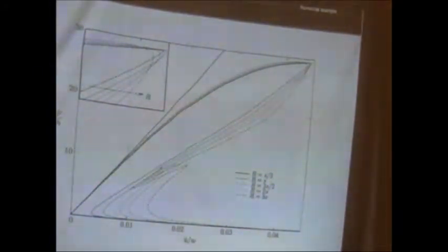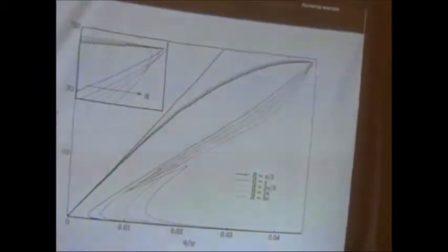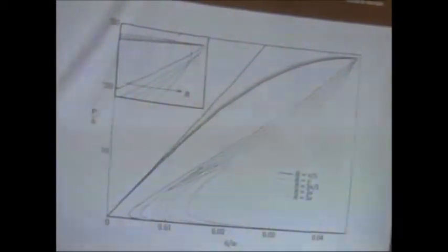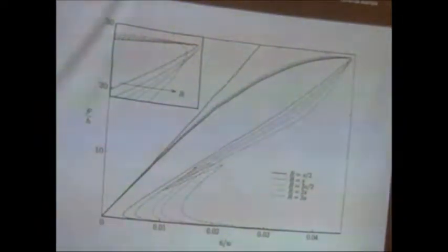which shows you another problem we face in quasi-brittle damage, which are so-called snapback problems. If we load this bar, then we see here the elastic regime, then it becomes nonlinear, and at a certain point it snaps back with a continuing damage evolution, and the stresses eventually reach 0. Then the damage is such that this bar doesn't withstand any load anymore.